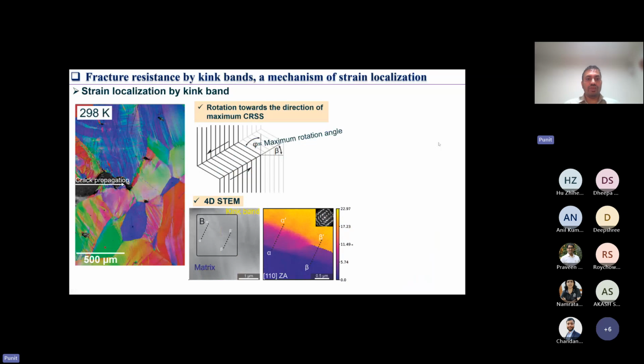So we wanted to understand what a kink band is. The idea of the kink band was first given by Orowan in 1948, and he talked about kink bands aligning edge dislocations, which rotates the crystal. But it was not really confirmed whether edge dislocations are what form these kink bands by lining up. So we did these 4D STEM experiments where we wanted to see what is happening across the kink band boundary, and we wanted to see if they are pure tilt boundaries or pure twist boundaries to confirm if they are made by edge dislocations.